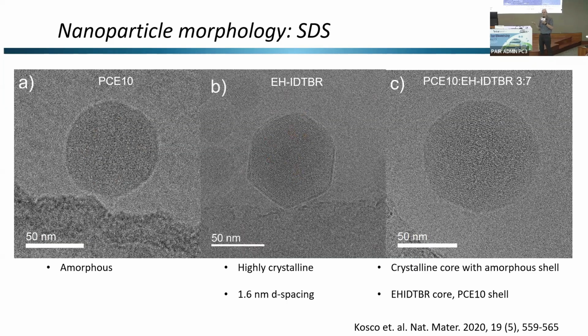And one of the reasons it forms such nice ordered structures is that in comparison to spin coating, when you make a thin film by spin coating for a solar cell, that's a very quick, rapid kinetic process. Solvent flashes off and you get the kinetically frozen product. Here, this takes a little bit longer. So there's more time for nucleation and growth. So you get very highly ordered structures here. And when we make our binary heterojunction nanoparticle, it's exactly what we would have expected. We've got our EHIDTBR core, and on the shell here, we've got the amorphous PCE10. So this is exactly what we'd expect.